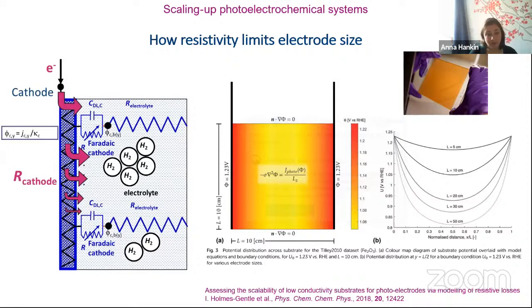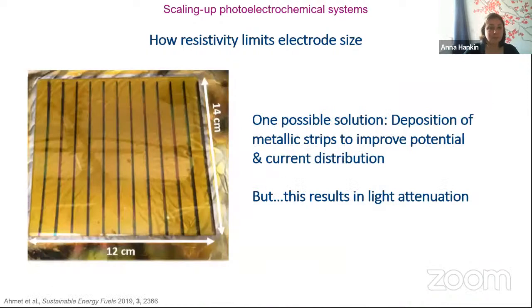Well, it's very limited. And the sketch on the left essentially illustrates why electrons don't want to go from where you have your electronic contact all the way to the end of a very resistive electrode. So you will have a much higher current density closer to the electronic contact than you will somewhere else. So it shows that scaling up such electrodes is actually not very sensible. You double the area, you don't double the current.